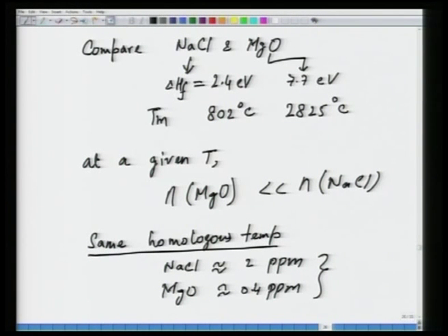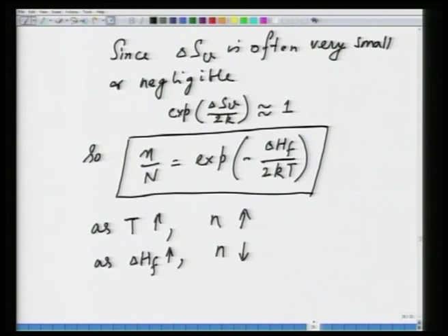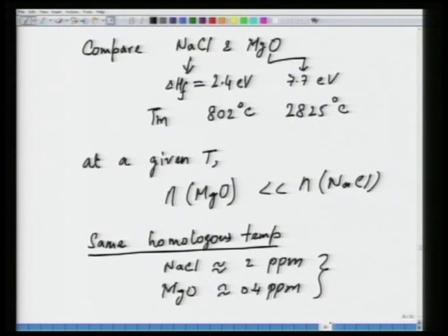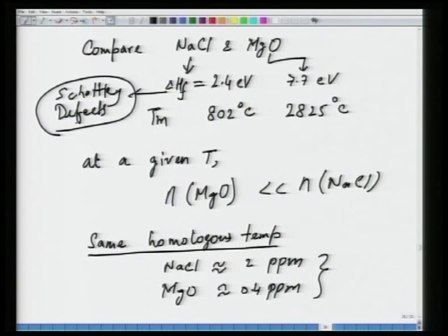However, these are intrinsic defects. Now, in the previous expression, we worked out this expression for Frenkel defects. A similar expression can also be worked out for Schottky defects, because there also you have a pair of defects. So, there is no difference. The only thing is that this will become delta H S in Schottky defects. So, when we talk about NaCl and MgO, delta H f is nothing but for Schottky defect, because both of the materials are prone to having Schottky defects. However, the derivation remains the same and there is no change.